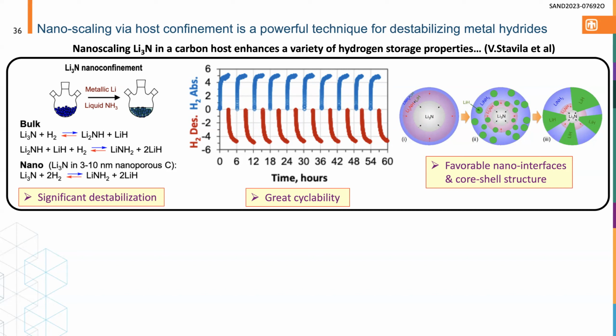In the middle there, you greatly improve cyclability of the material. So that's a really good number of cycles for a complex metal hydride there in the middle. And there's been a lot of theory work that looks at why these are the cases, and it's very complicated, but it gets down to the fact that you form favorable nanointerfaces and this core shell hydriding structure that synergizes to make all these great benefits.